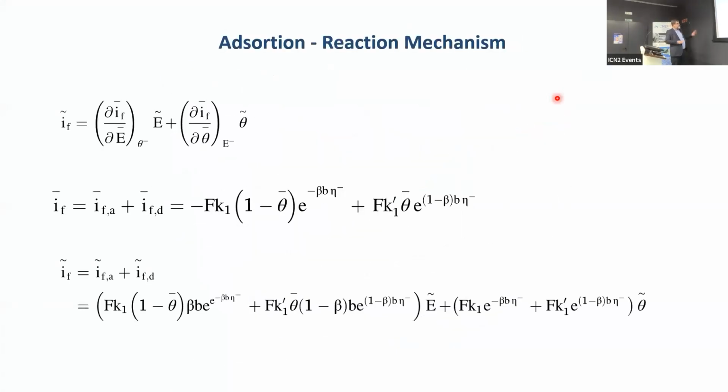And to investigate the kinetic process, kinetic studies, we have used impedance. In this case, we have considered only the charge transference and hydrogen adsorption at the surface. So we have used the Langmuir isotherm and Butler-Volmer at the steady state and at the oscillatory state.